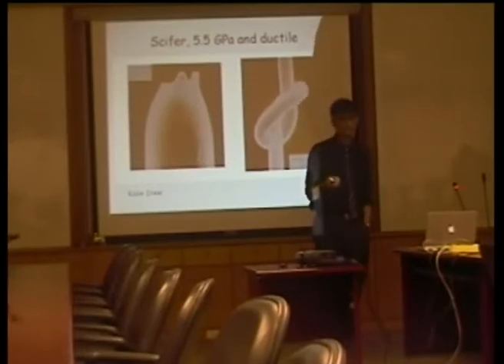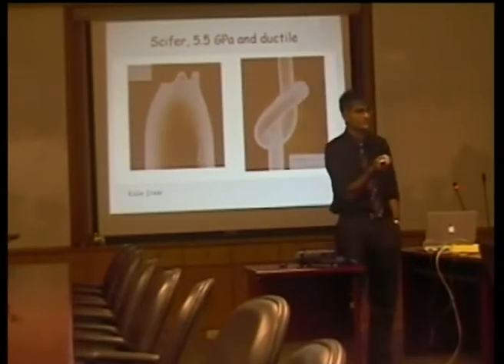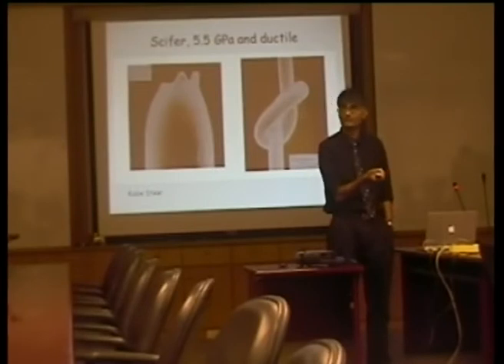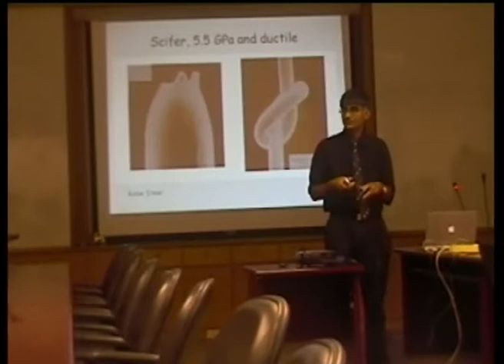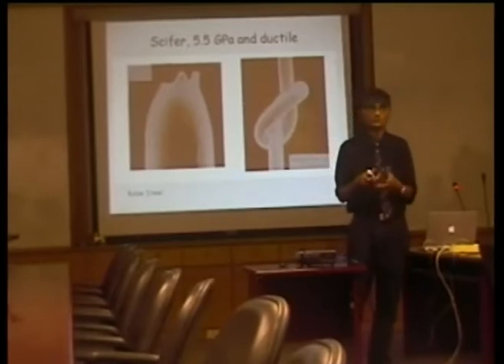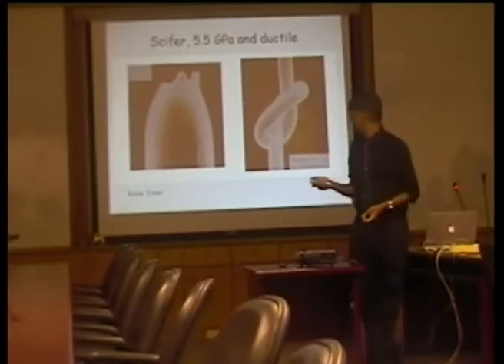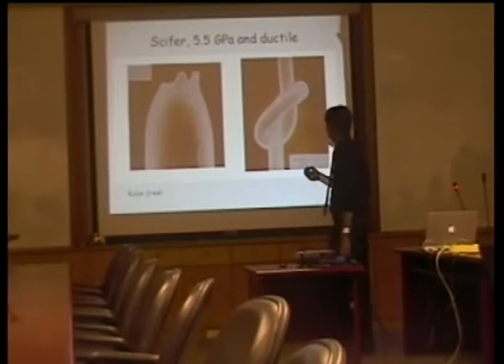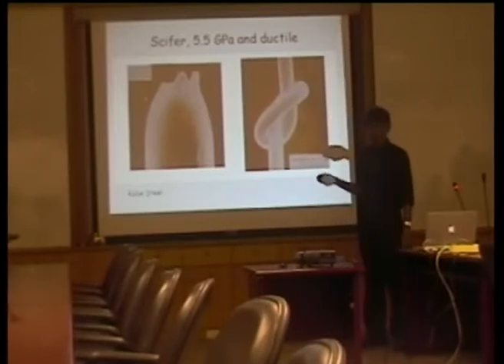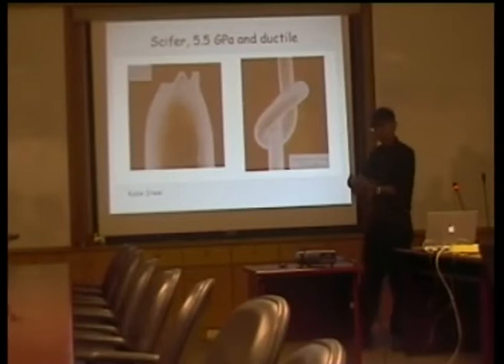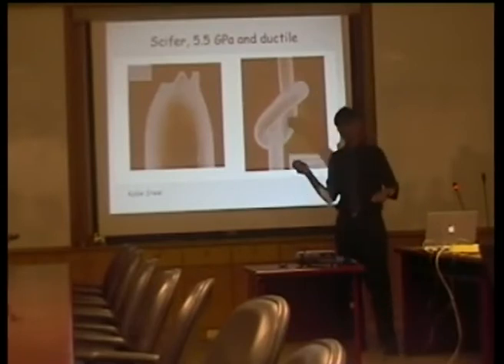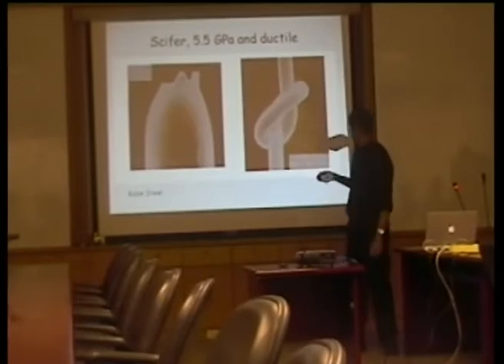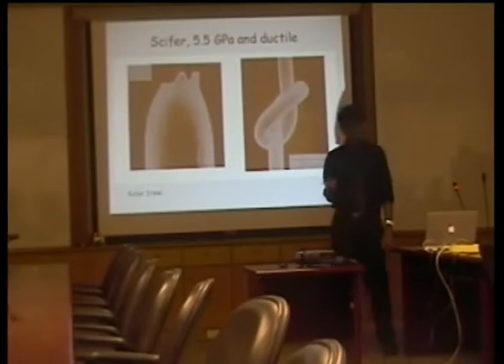Now, one of the advantages of having a very fine grain size is that you don't lose ductility. If I increase the strength by forcing carbon into solution, then the ductility decreases. The material becomes brittle. Here you can see that even at this strength level, it's very ductile, and you can even tie a knot with it. You couldn't do this with carbon fiber. Carbon fiber has zero ductility and a strength of about 3 gigapascals.